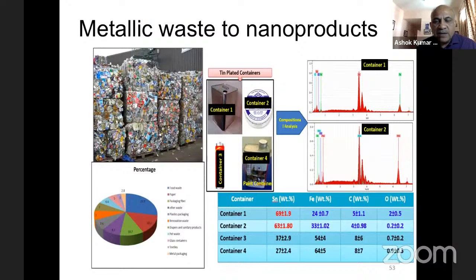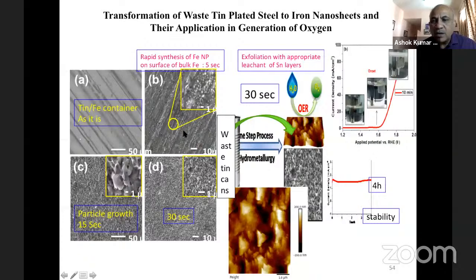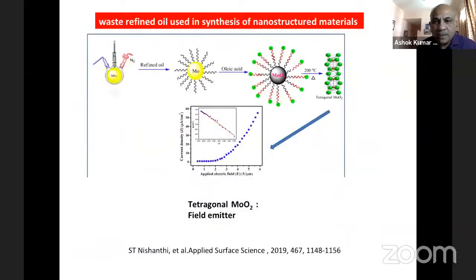In waste to wealth, we took tin containers. A lot of tin containers are in the market. We took them and converted them into a catalyst. Most of the tin container is iron coated with a little bit of tin. So it becomes iron oxide and tin oxide, and that you can use for oxygen evolution reactions. This is waste to wealth. So from waste tin plated steel, we made a catalyst which can generate oxygen.